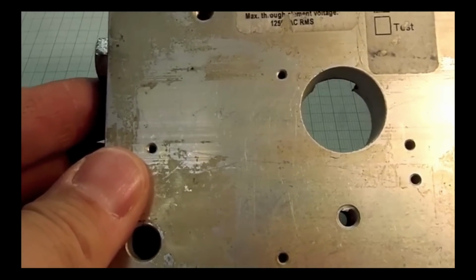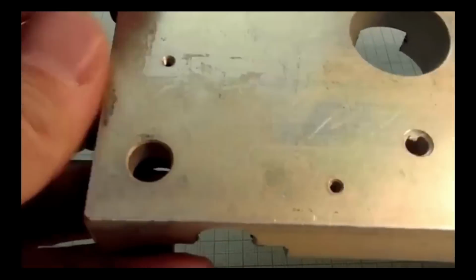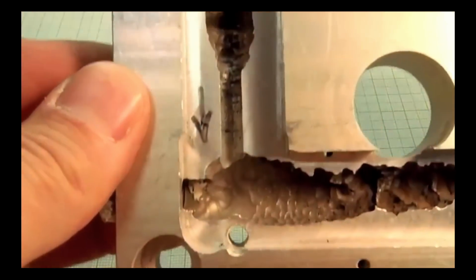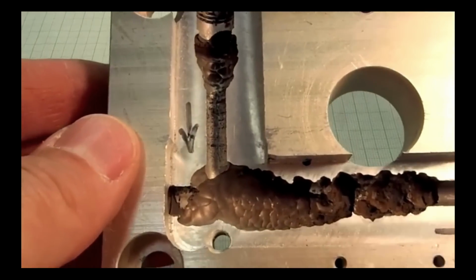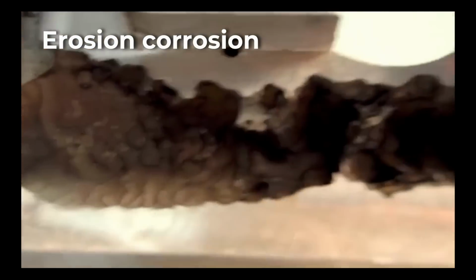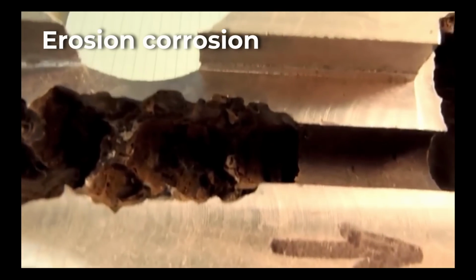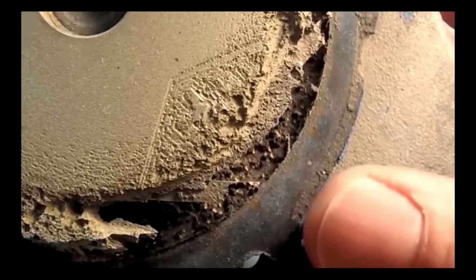This aluminum plate was used as a heat sink for electronic equipment. Cooling water flowed through it. As we can see on the cutout side, everywhere the water hit turbulence, it became very turbulent, especially at these elbows, and we had a whole lot of metal loss. This is called erosion corrosion.